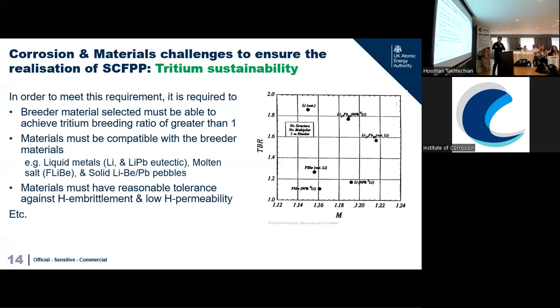Of course, the materials we use have to be compatible with, in this case, lithium. It's highly reactive. Not many materials survive when in contact with lithium. And materials must have reasonable tolerance against hydrogen embrittlement, and low hydrogen permeability. Again, we are breeding tritium, which embrittles our materials. This morning it was mentioned that hydrogen gas doesn't react, but we are breeding tritium atoms. It will basically react with our material and cause hydrogen embrittlement.